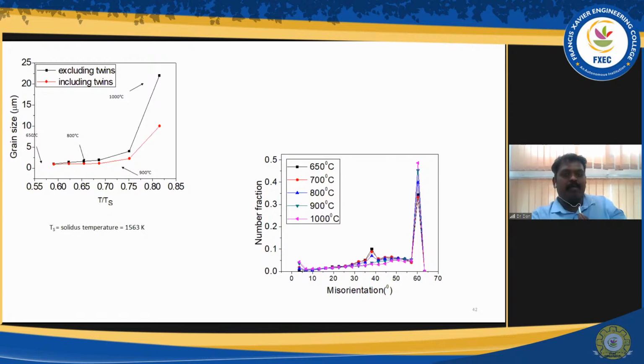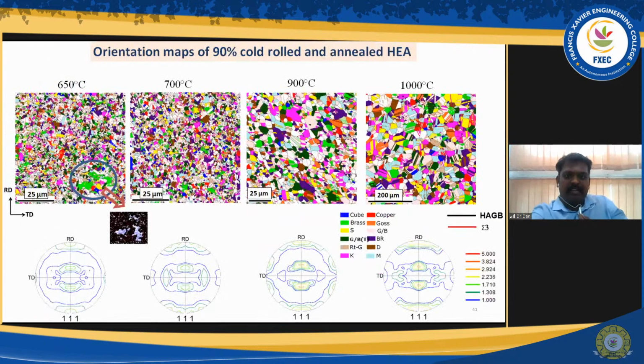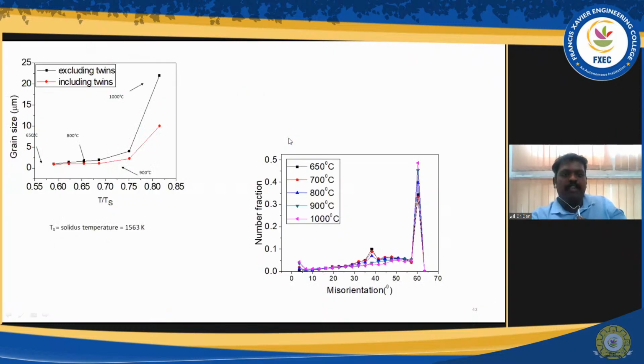Here I try to show some of the grain boundary characteristics. In the sample, you can see the red color lines. What I showed here is mainly due to twinning: during recrystallization, many annealing twins form in this alloy, and that also leads to the very small grain size. In the case of 700 degrees Celsius, I got 800 nanometers including twins. By twins, I mean sigma 3 boundaries. In the misorientation angle diagram on the right side, you can see a peak at 60 degrees, which indicates that your sample has a large number of CSL boundaries. CSL boundaries are sigma 3 boundaries.